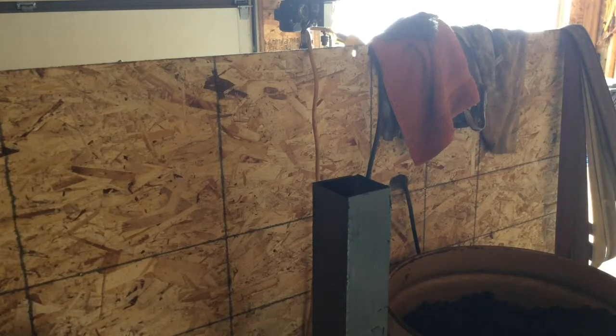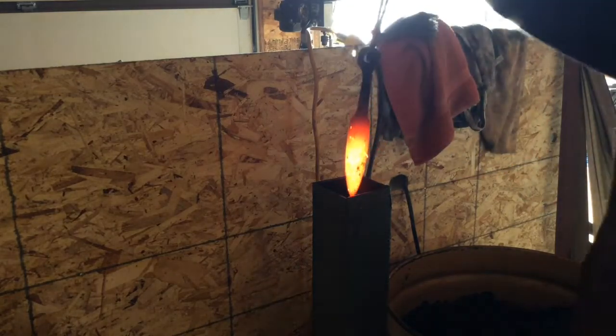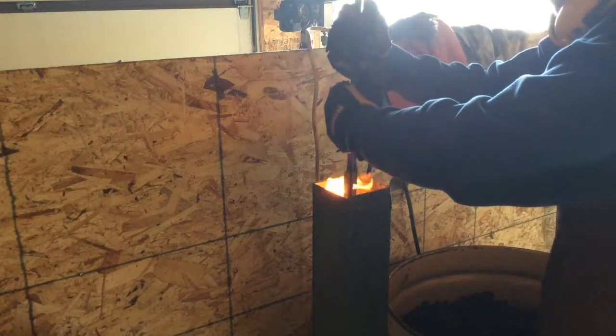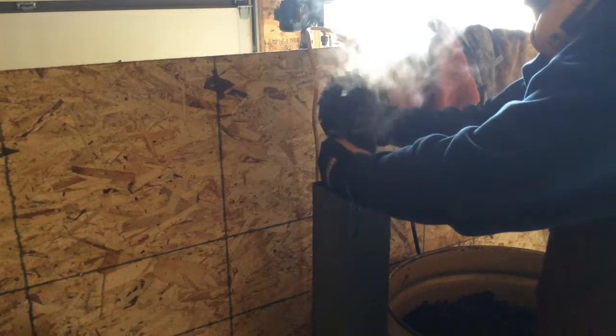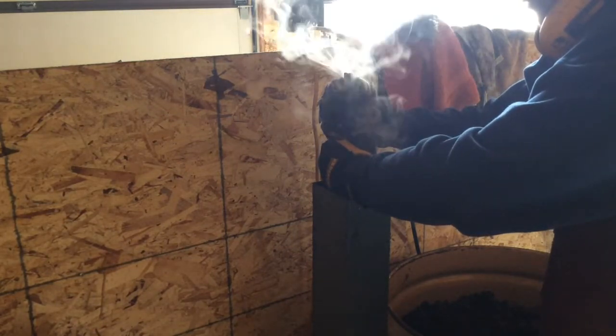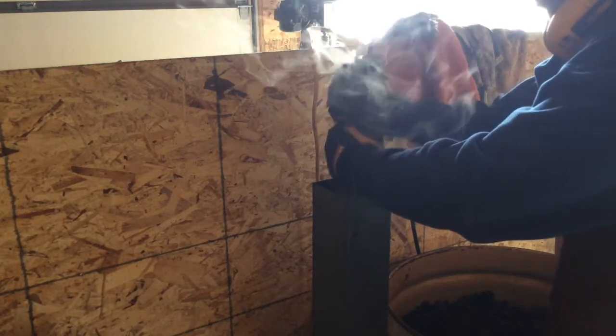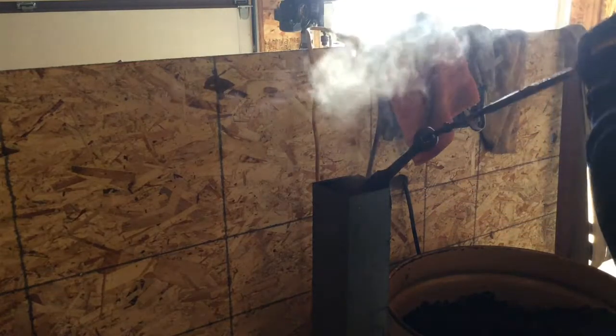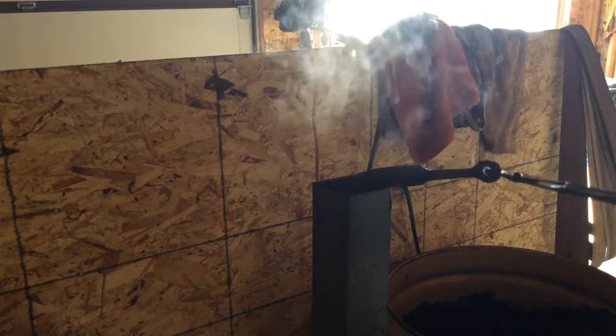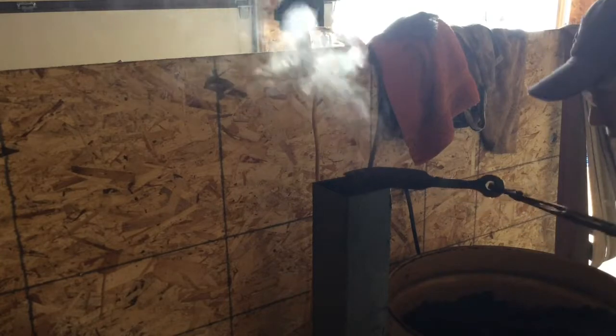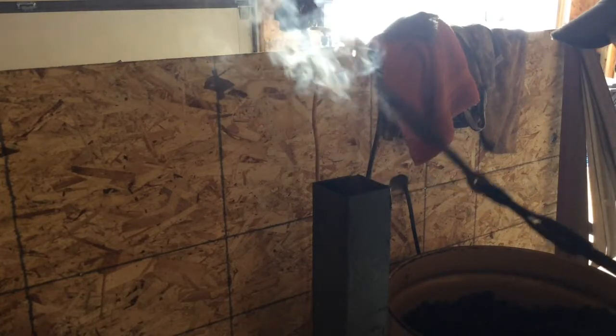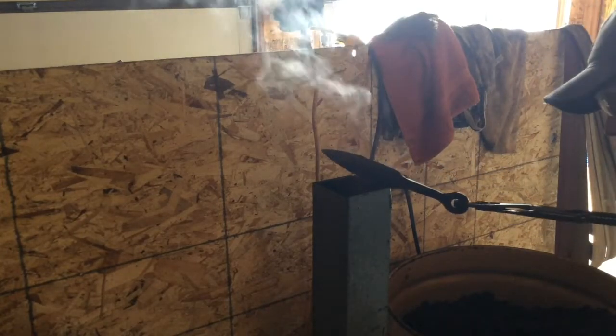Now I am hardening the blade by heating it up to about 850 degrees Celsius and quenching it in oil. This makes the steel very hard, but also very fragile, so I will have to temper it after, which is heating it at a lower temperature to make it tougher. Since this is a throwing knife and will experience a lot of shock, I'll temper it more than I normally would a knife, so that it is more springy and will be able to withstand a lot of energy without bending or snapping.